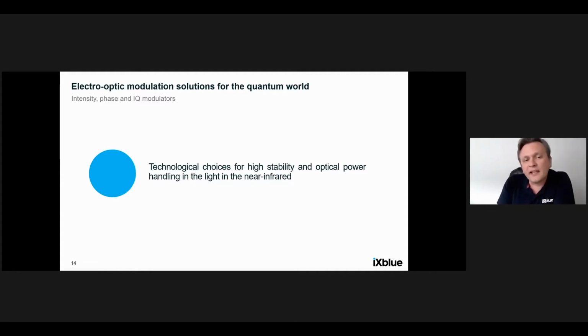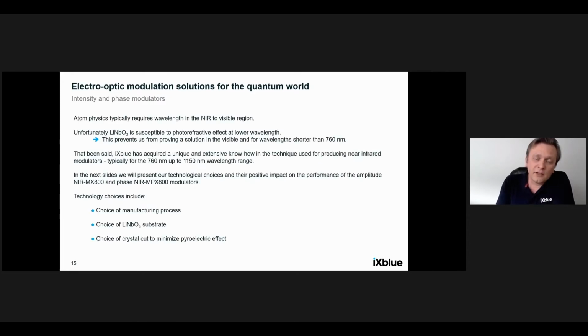Now, we have made at iXblue a few technical choices that provide high stability and high power handling, especially in the near-infrared. So in the quantum world, typically people are looking for solutions in the near-infrared or even visible. Unfortunately, lithium niobate is susceptible to photorefractive effects at lower wavelengths. So this prevents us from providing solutions in the visible and for wavelengths shorter than 760 nanometers. Now, that being said, we've acquired a unique and extensive know-how to make very good electro-optic modulators in the near-infrared from 760 to 1150 nanometers. And in the next slide, I'll go over the details of what technology choices we have made and how we became a leader in that field.